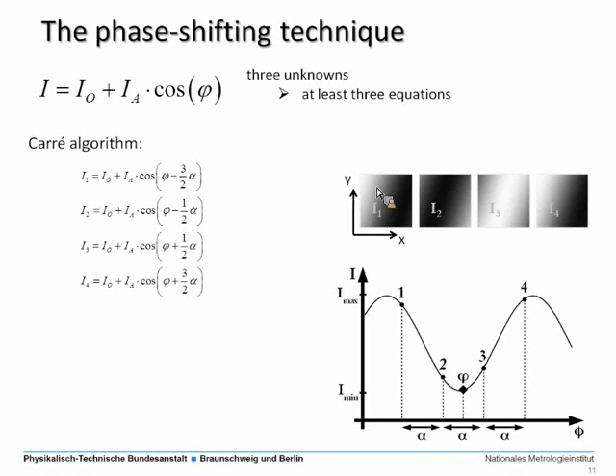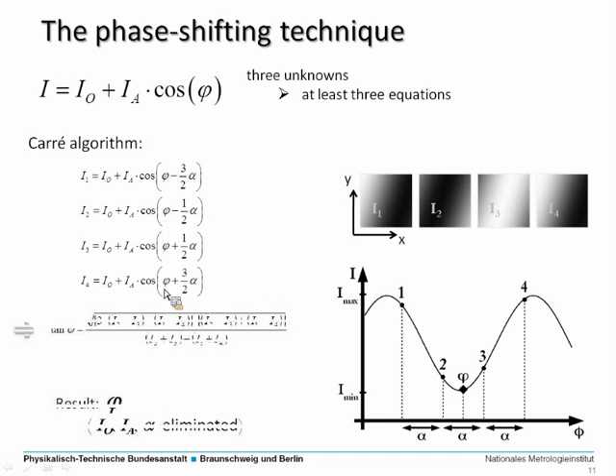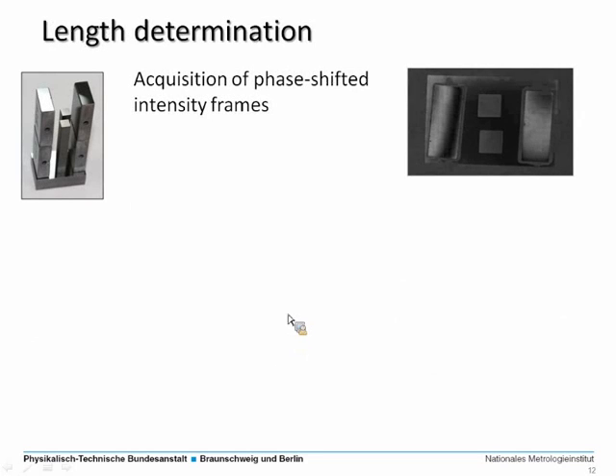And if you look now at one of these pixels, for example here in the upper left corner, you see this mid-gray value, maybe this one here. You apply a phase shift in the reference path of the interferometer, for example. Then this fringe pattern shifts a little bit, and you get a darker intensity value. If you apply the next phase step, you get again a gray value, and in the fourth image a brighter one. This is just an example for 1 pixel, but what you can do then is use this system of 4 equations in order to solve for phi, which is the phase. And as you can see, these other quantities are eliminated from this system, and you get the result of the phase. And this is what you need for the length determination.